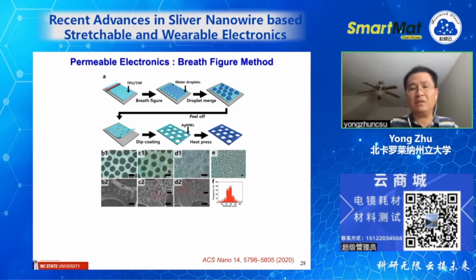The water will condense on the substrate, and then they will self-assemble into droplets. Then, when the solvent evaporates, they will essentially form a honeycomb on this substrate. And then we want to coat the nanowire. We just dip coat this into the silver nanowire solution, and then we heat press. So in this case, the nanowires will be heat pressed into the TPU substrate.